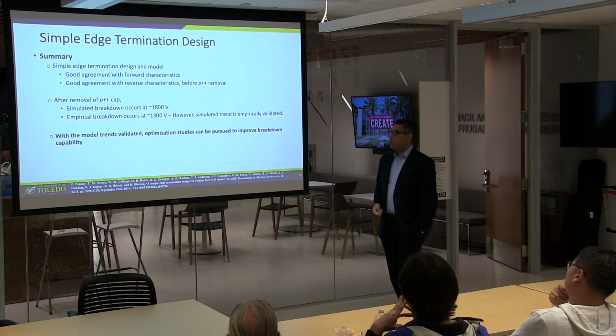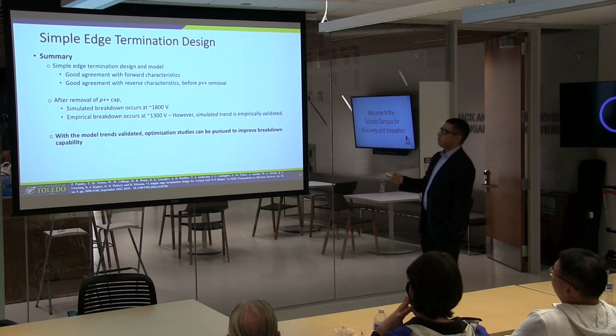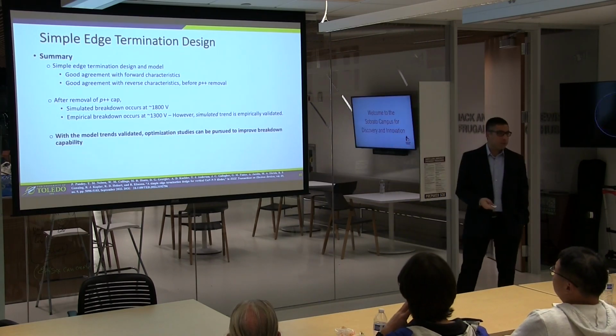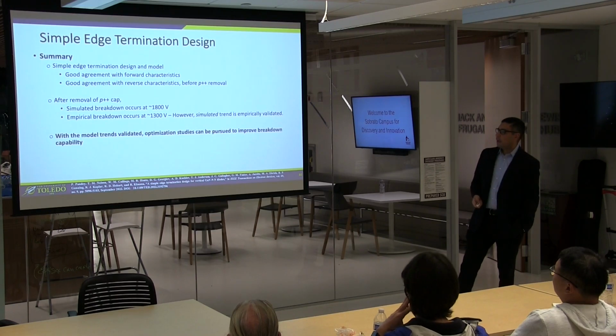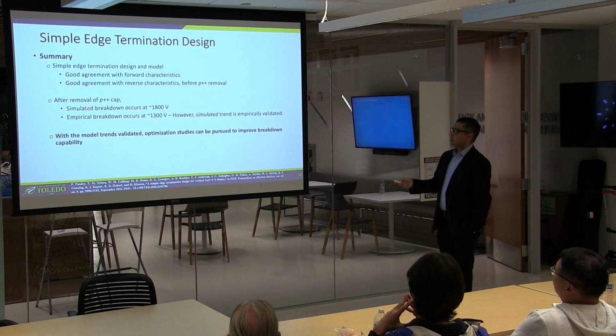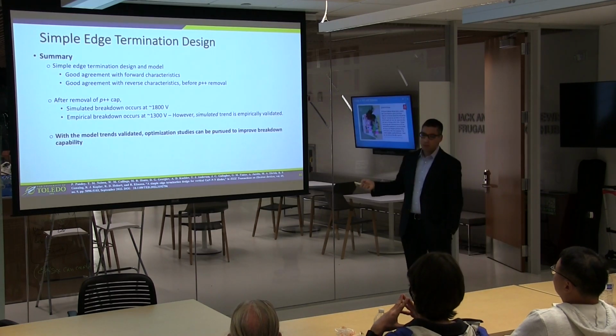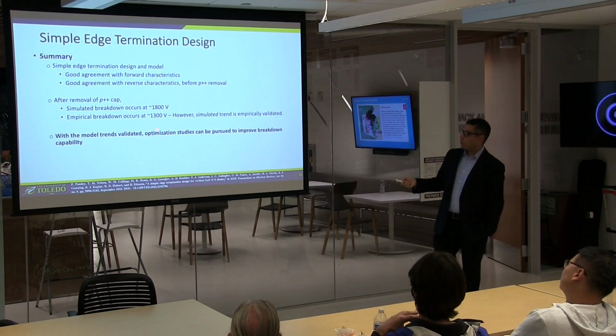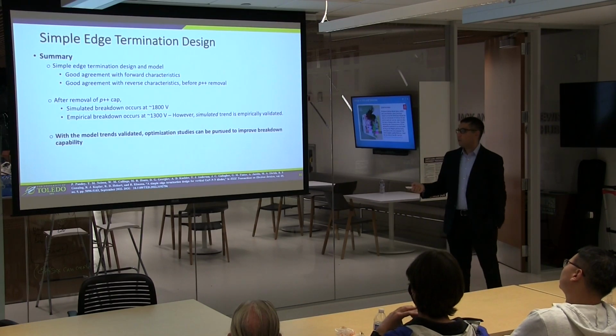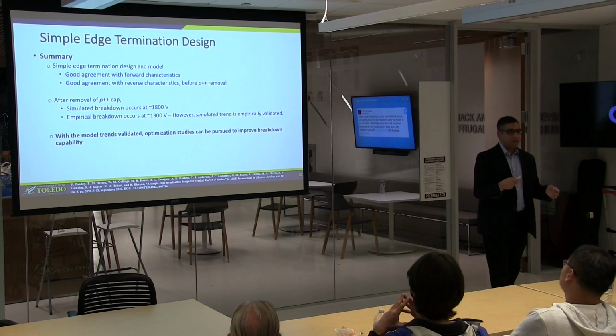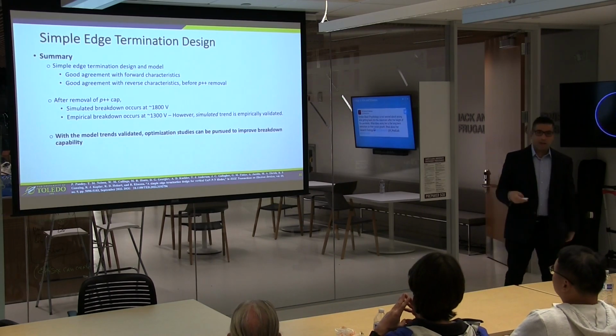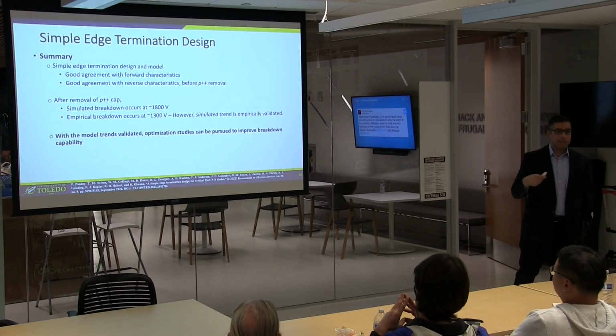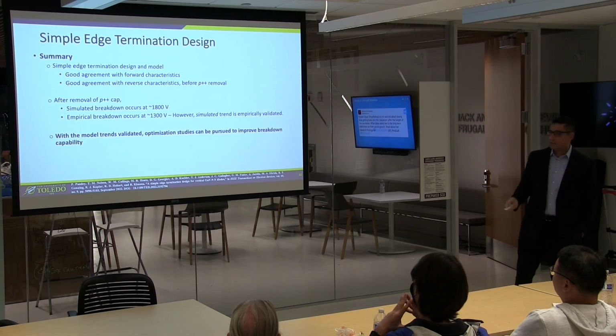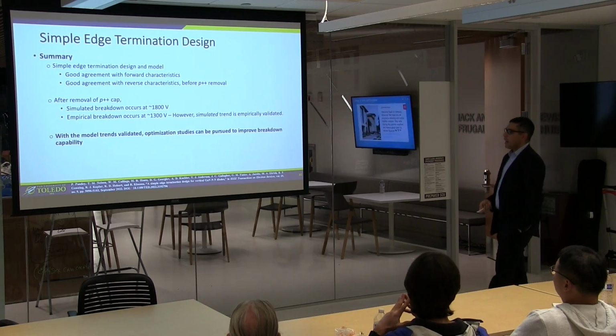So, in summary, what you have there is good agreement with the forward characteristics with TCAD, and good agreement with the reverse characteristics with TCAD. After removal of the P+ cap, the breakdown voltage of the simulation was 1800 volts. The empirical breakdown was about 1300 volts. There might be some etching defects when they're etching that away, so we need to work on actually capturing all those effects when they etch it. That's why there's a difference between 1300 and 1800.